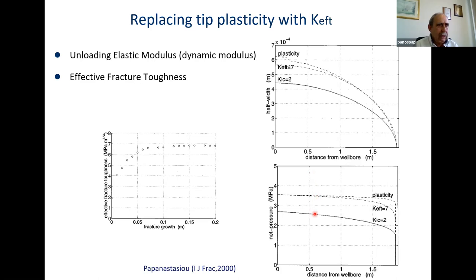And this is what we did here in this diagram. The initial fracture toughness before propagation, the elastic fracture toughness, I will say, was 2. And this was the prediction by the elastic model. If we use the effective fracture toughness, the limit value, the pressure profile is this one here, as you can see. No, actually, this is not the pressure profile. This is the fracture opening.